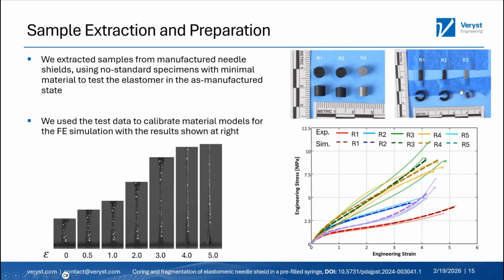These are cylinders that we extracted from the rigid needle shields. You can see they're about 5 millimeters by 5 millimeters in size. And then over on the right, there are strips that we extracted, again, from those rigid needle shields to get tensile specimens. You can see those strips are maybe 15 to 20 millimeters long and have a width and thickness of about 3 to 5 millimeters. So we have pretty small samples that we wanted to test.